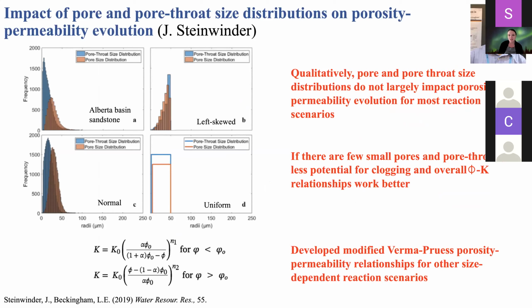And we found that qualitatively, these pore and throat size distributions don't really impact porosity and permeability evolution for most scenarios. But if you did have a sample that had really few small pores and pore throats, such as this synthetic left skew distribution, there's going to be less potential for clogging, and overall those porosity permeability relationships are going to work better. In this paper, we also developed this modified Verma-Pruess porosity permeability relationship that did work well in the size dependent reaction scenarios, and what was plotted as those red lines on those last plots there.